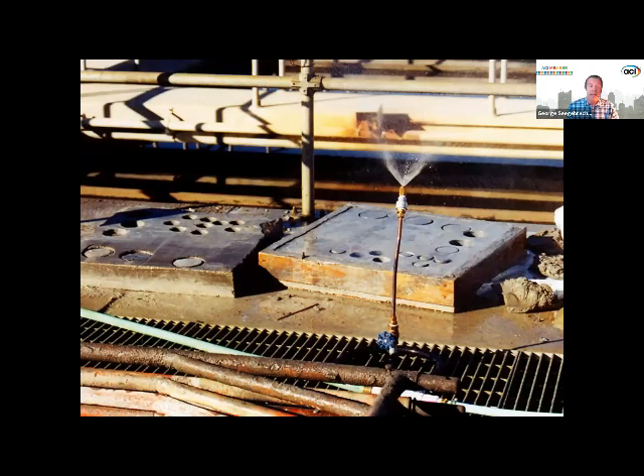We even had test panels with field cores that we extracted at the days from the site just to keep as close to what we were doing, because this was a very thin overlay of concrete that had been quote unquote corroded, not in the corrosion of steel way, but due to the low pH of the effluent that's in those tanks. It kind of softened the surface and compromised it. So we removed that with hydroblasting and put back a shotcrete overlay.